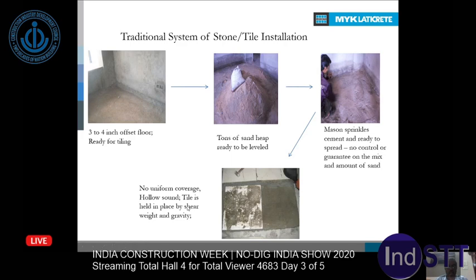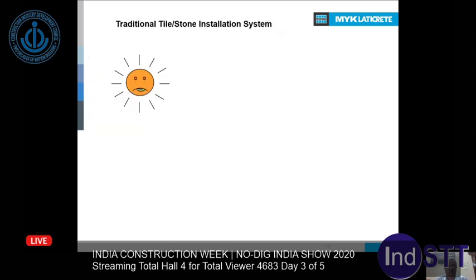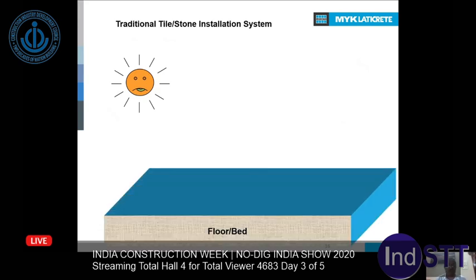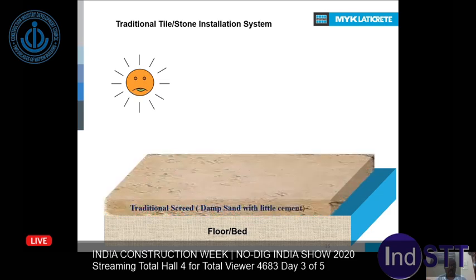And again, it matters what kind of tile, what kind of format you're using. If you're using very highly absorbing tiles, then the cement slurry may be good enough to hold the tiles, with good bonding. But if you're going to use a low absorption or vitrified tile or stone, then it will not bond at all. Here you can see in the pictorial what happens when you put the cement slurry on the cement sand bed. This is a traditional screed, basically damp sand with a little cement.